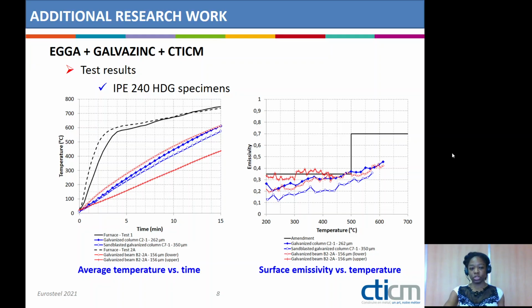We can have the same conclusion when we take a look at IPE 240 hot dip galvanized specimens. So you can see that after 15 minutes, the temperature can reach up to 600 Celsius degrees on the web and on the bottom flanges of the beams and of the columns. And when you consider the upper flange that was not fully fire exposed, the temperature stayed below 500 Celsius degrees after 15 minutes of standard fire exposure. And applying the reverse method leads this time to surface emissivity values that are lower than 0.4. So they more or less confirm the values that were proposed in the amendment to Eurocode 3 and 4 regarding the temperature calculation of fire-exposed steel members.